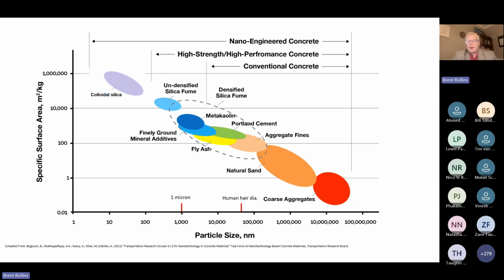Then when you start getting into high strength or high performance concrete, you start using finer and finer ground materials to make sure that the particle packing takes place properly. That's a key to both permeability and strength development in some of these high strength mixes. You start using some exotic pozzolans or supplementary cementitious materials like calcined clays, metakaolin, etc. Silica fume is another one of those exotic pozzolans. And I say exotic just meaning not often used.